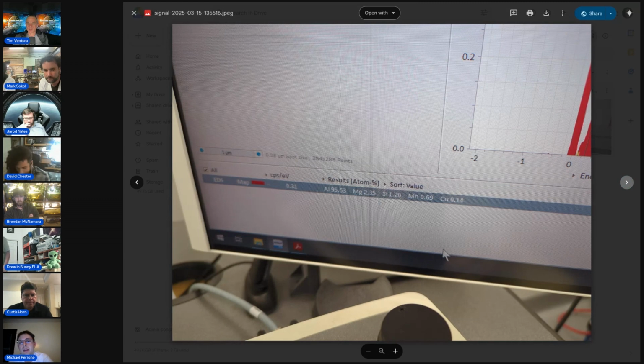That's in line with many aluminum alloys, but I'll have to double check which alloy it would specifically be. And with the carbon and oxygen removed, because we suspect that those are from the surrounding epoxy, it's basically 95% aluminum, 2-point-something% magnesium, with a little bit of silicon, a little bit of manganese, maybe some copper, but basically under 0.5%. You really can't trust EDS data too much.